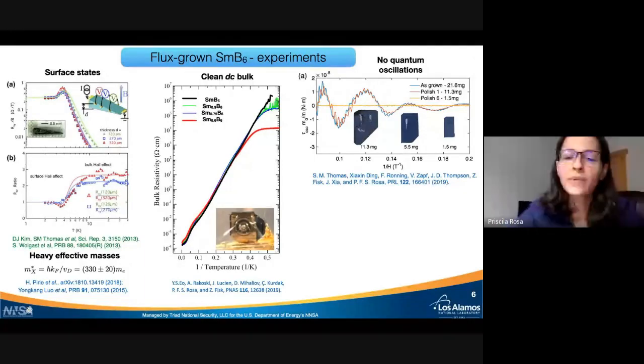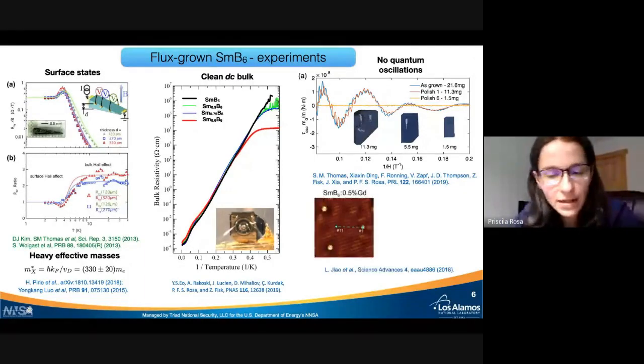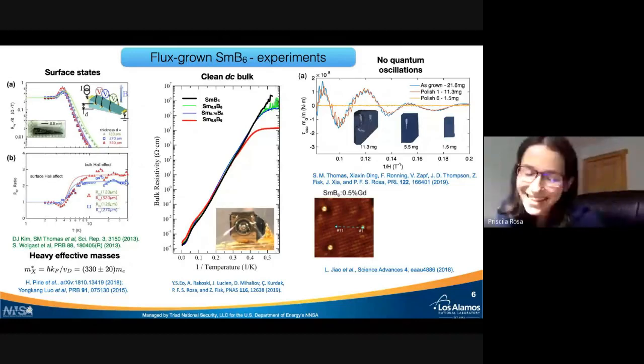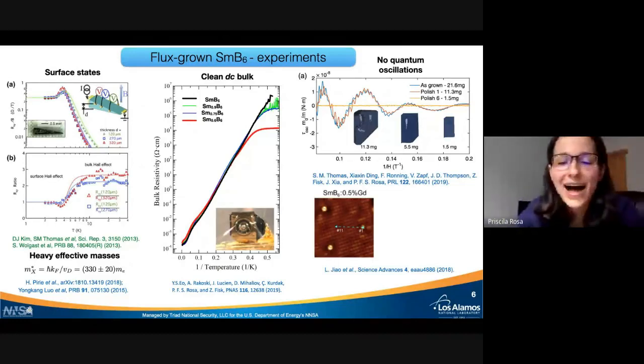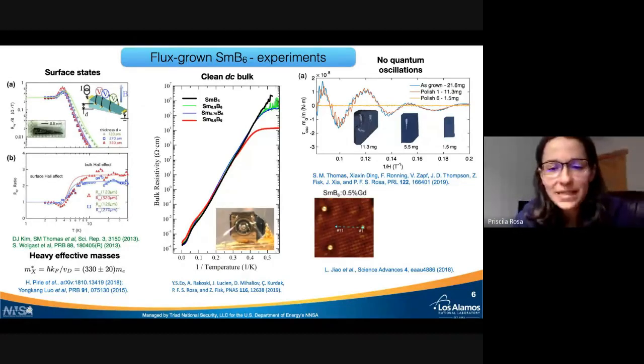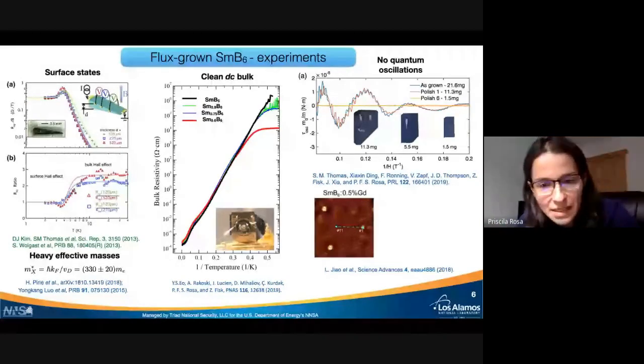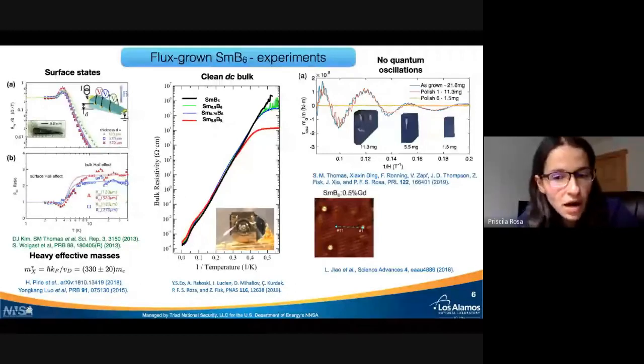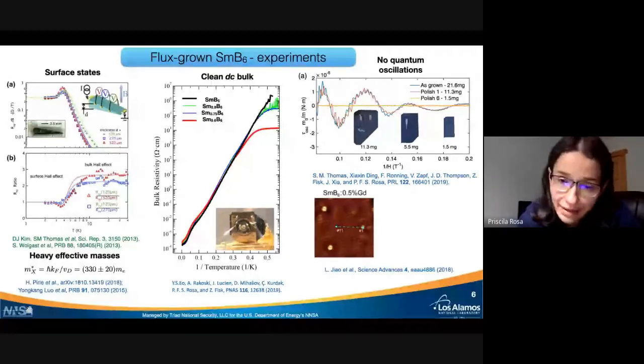So finally, let me tell you about scanning tunneling microscopy. So these are samarium B6 crystals with a little bit of gadolinium in them. So we're looking here at the surface of samarium B6. You can see here the atoms very, very nicely spaced. And these bright spots are gadolinium impurities. And why are we adding gadolinium?